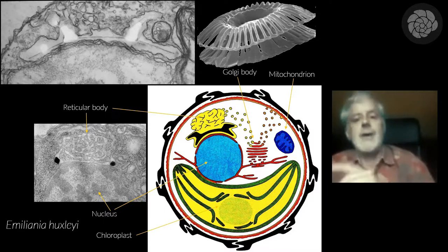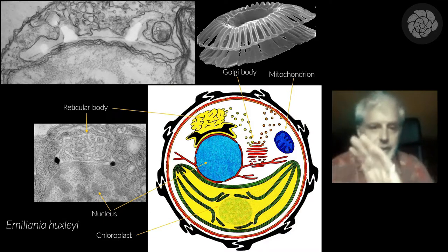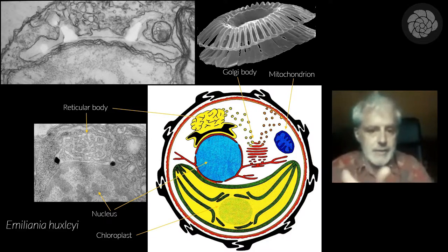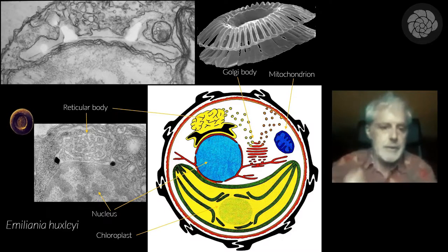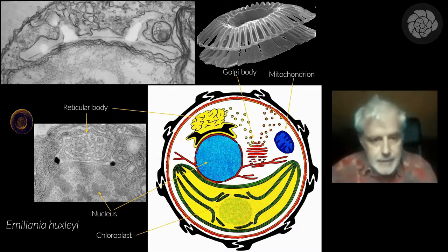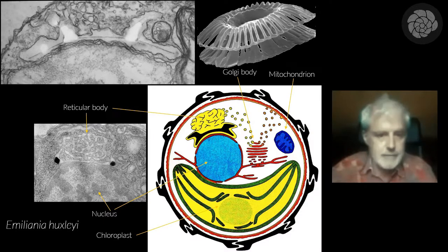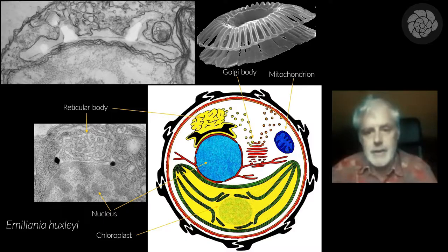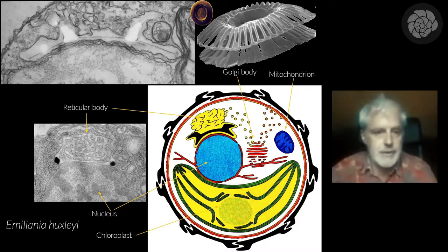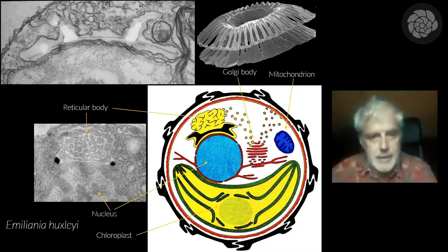However, the cool part, in terms of how those coccoliths are forming, is that it's a two-phase process. First, they nucleate. There's the initial phase of calcite nucleation, where very simple little rhombohedral crystals form. You can see them here. This is in Emiliania huxleyi as a sketch section, and then these are transmission electron micrographs in thin sections showing it forming, then getting larger. And that was one way in which they've been studied, by looking at thin sections like this across cells.